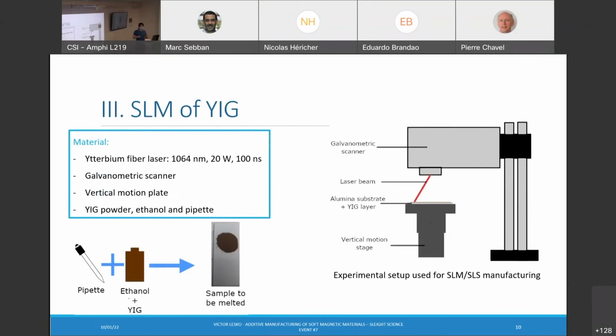At this time, we don't have the powder bed setup. We are using this setup, which is made from a galvanometric scanner, and we are using an ytterbium fiber laser in the infrared to melt our powder. And as we don't have the powder bed system, we are using a suspension of YIG powder in ethanol. Then we take this suspension with a pipette, and we drop it on our substrate. The ethanol evaporates, and only a thin layer of powder remains.